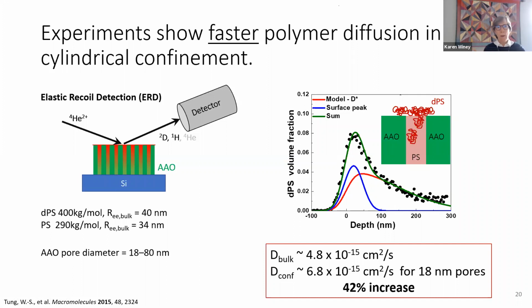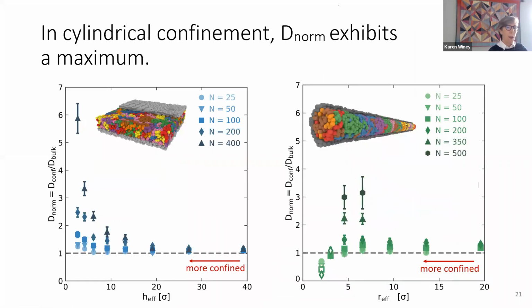We looked at different molecular weights and different pore sizes, but here's an example. The diffusion coefficient in the bulk is 4.8 times 10 to the minus 15 centimeters squared per second. In the confined system, an 18 nanometer hole, the diffusion coefficient is 42% higher. So things are getting faster when you diffuse into pores. This is what we went after in the simulations, and we kind of saw that, but we saw something else that was quite interesting.